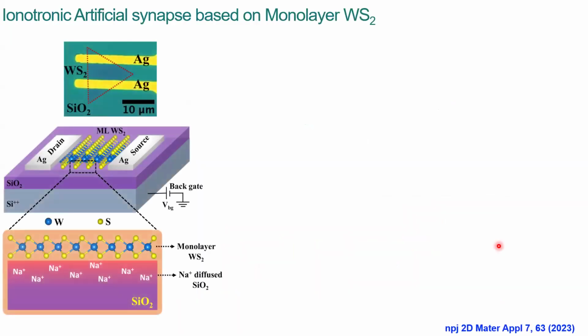And lastly, I would talk about this ion-based artificial synaptic device. Here we have used a CVD grown WS2, which is a triangular WS2, and this is a monolayer. And we used Ag as a source drain contact. And during the CVD growth deposition, we